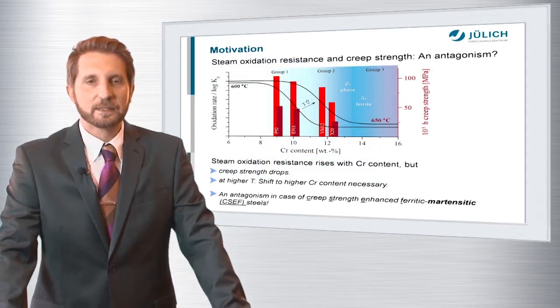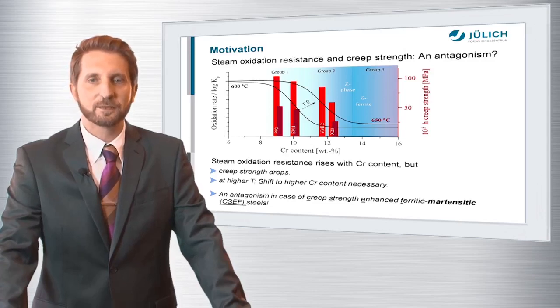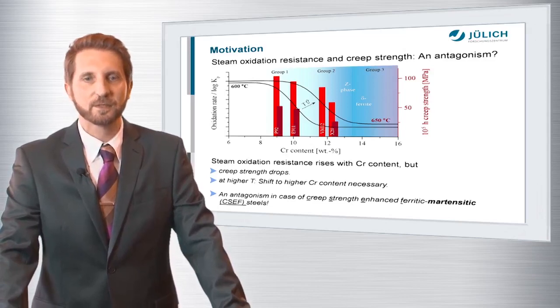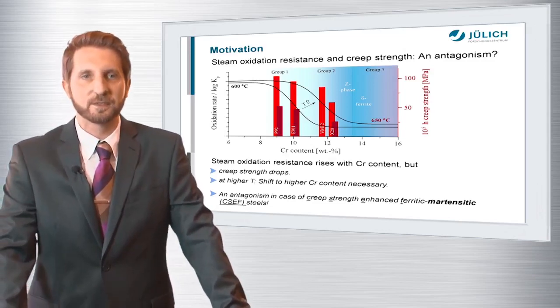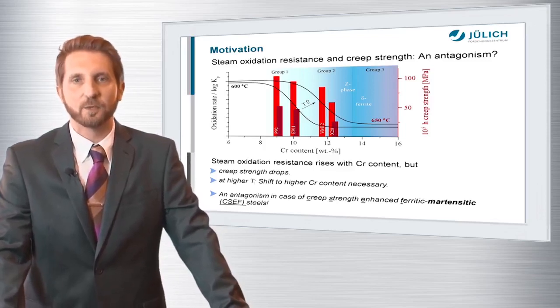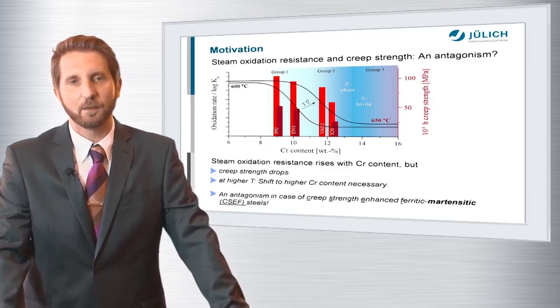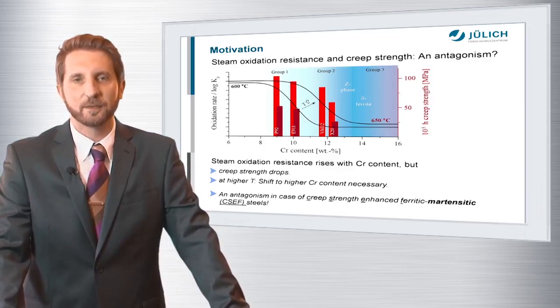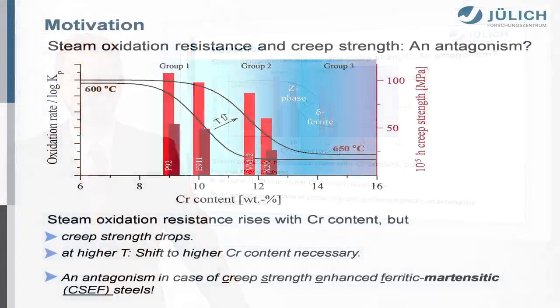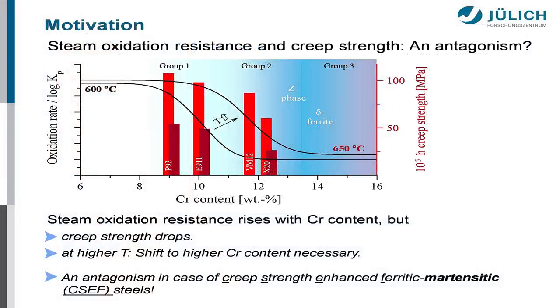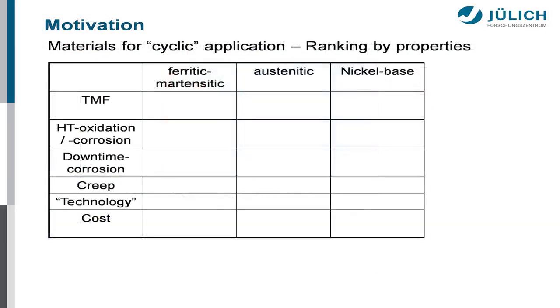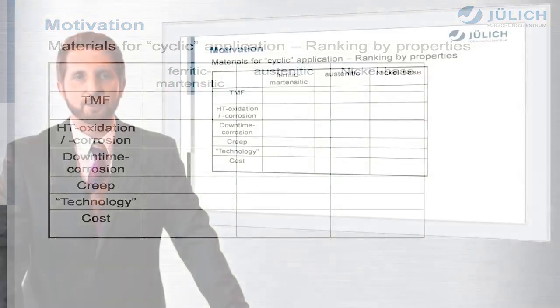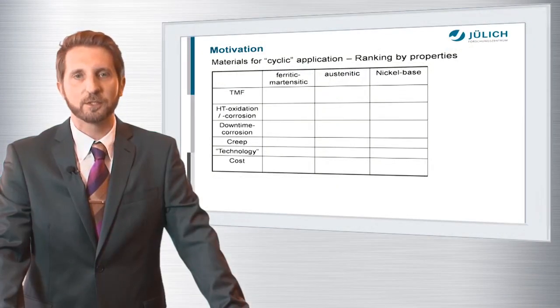So to summarize this, in case of the state-of-the-art creep strength enhanced ferritic martensitic 9 to 12 chromium steels, creep strength and steam oxidation resistance together seem to be an antagonism, and that is one of the main reasons why most, or let's say all, the efforts in creating new high-strength, sufficiently steam oxidation resistant 9 to 12 chromium steels failed during the last 20 years. So having a look at the material classes that are available for power plant application, for structural application in thermal power generation, the most important material class today is the ferritic martensitic steels I've been introducing to you.